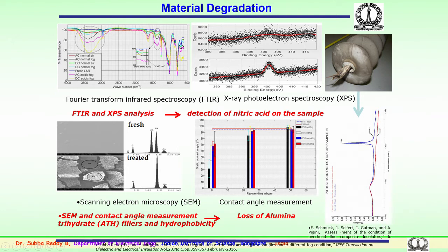Similarly, contact angle measurement is very important. Hydrophobicity performance of the insulators has been measured over a period of time, and this has been very clearly given here for various types of materials and their performance over a period of time. So, fresh, with moisture and with acidic fog, the performance has been seen and how the recovery has happened over a period of time. So, recovery time versus the static angle, that is the angle which the sample shows when the water droplet is put on the rubber sample. There is a standard for the hydrophobicity measurements. The performance is verified and estimated. This is a very important aspect for the detection of the hydrophobicity effect.